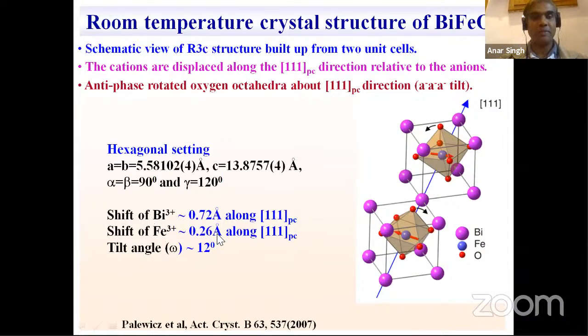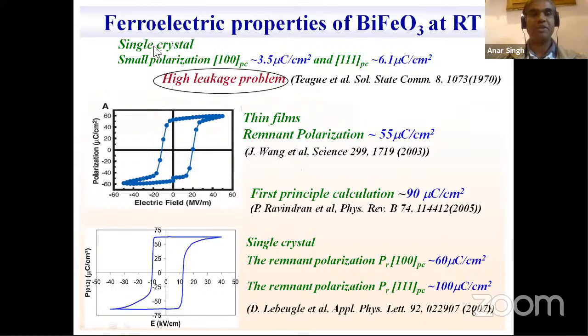Despite the large shift of cations, the ferroelectric polarization observed in bismuth ferrite was very low, nearly 6 microcoulomb per centimeter squared. This low value of ferroelectric polarization is because of the high leakage current problem in bismuth ferrite, because Fe can have +2 or +3 states, so there is an exchange of electrons, and that reduces its ferroelectric polarization. But later some insulating thin films were grown, and single crystals, in which large ferroelectric polarization close to 100 microcoulomb per centimeter squared was observed.